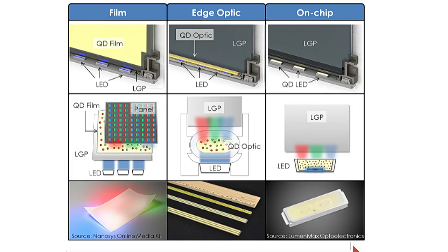In this situation, the quantum dots are at a much lower temperature because they're further away from the LED light source, probably closer to 50 degrees C. And they're also seeing a lot less light. So the quantum dots don't have to be as good, but you still need to use very expensive barrier films, because quantum dots are sensitive to oxygen and moisture. Without barrier films, the quantum dots would get photo bleached and would essentially not be usable for a product.